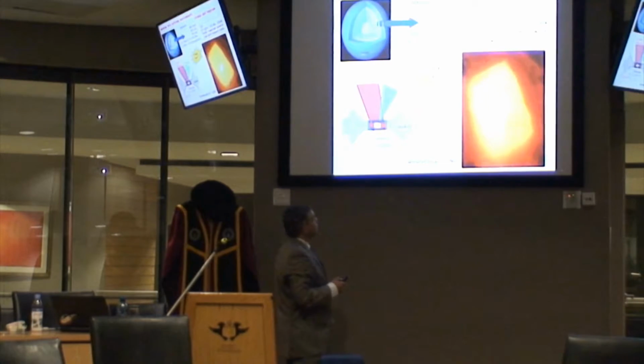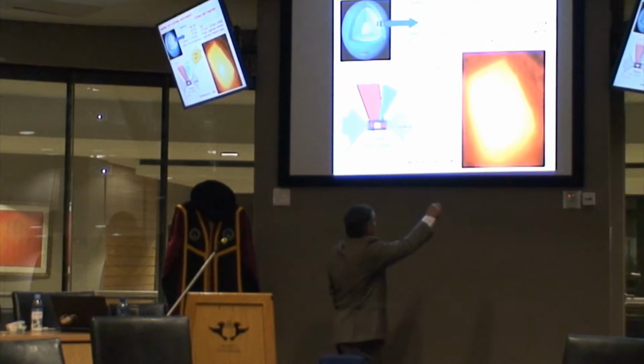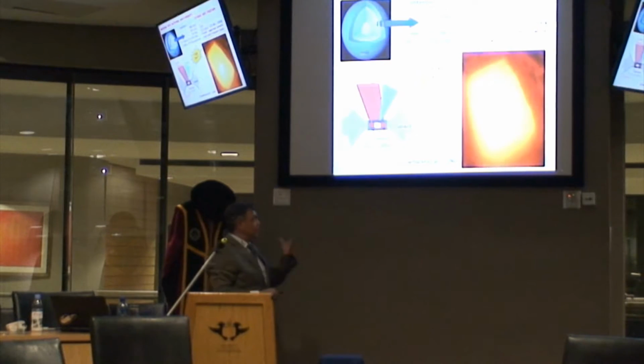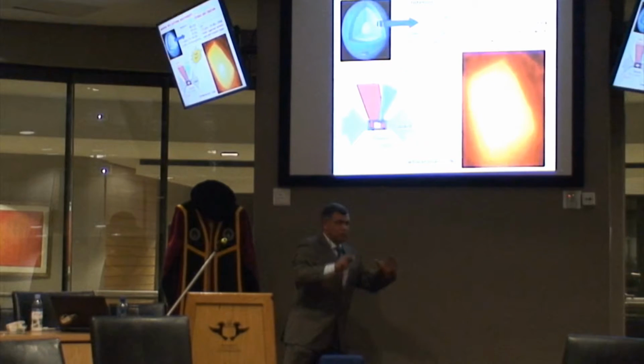And this is the effect. Over 2,000 degrees, over a million atmospheres, and what's important to notice, the profile of the crystal remains intact. It remains as solid ice without melting. Okay, so it really shows how this can be a window. It's hot ice, in fact, if you can picture that and understand that. This structure has been solved to be quite an exotic network of hydrogen and oxygen.